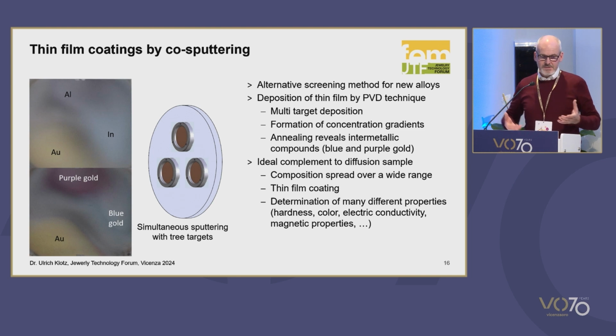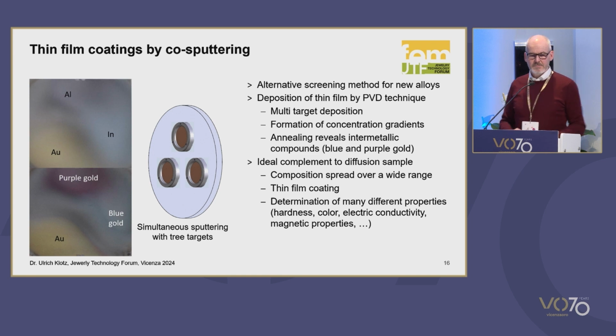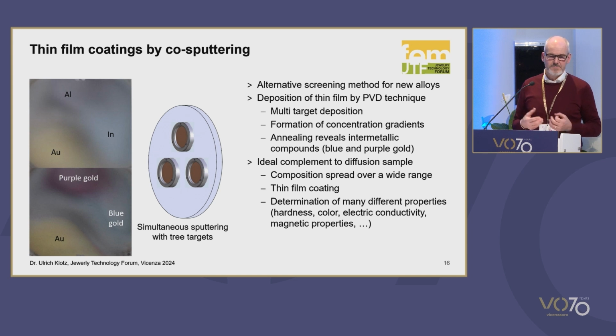And now we can anneal this glass plate, and we find the blue and the purple color forming. So the lower image is in the annealed condition. And this also helps us to screen interesting composition ranges. And now we can use different mixtures of sputtering targets to determine the resulting color. But of course, we can also measure other properties like the hardness, electric conductivity, and so on, quite similar to the diffusion couple.